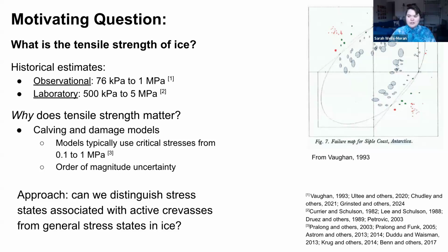And another important question is, why does tensile strength matter? It matters because of the models we use. A lot of large-scale ice models use calving and damage as one of the methods by which ice mass is lost. And a lot of models have a critical stress threshold that they use to simulate when damage or a calving event will occur. A lot of models use values ranging from 100 kilopascals to 1 megapascal. So again, very large range. This introduces a lot of uncertainty into these models.